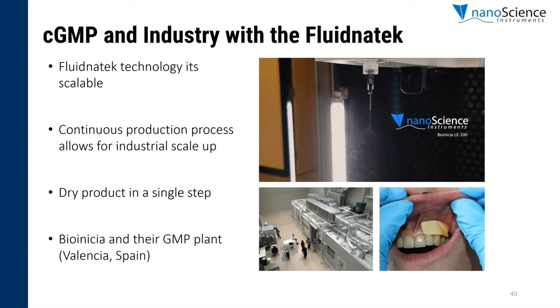Another important aspect about this technology is that it can produce a dry product in a single step, which is really important when using organic solvents because a lot of them can be toxic, for example, hexafluoroisopropanol or chloroform. Our units are GMP certifiable and scalable, allowing the technique to be even scaled to a production plant. We can easily increase the number of spinning heads along with the size of the machine, increasing the production rate into the industrial scale. As a matter of fact, Bioinicia has the first and only GMP certified plant to produce fibers for pharmaceutical applications and is currently working on developing a second GMP plant for particle development. Just as an example, with all these three images, we can go from only 1 emitter to a production plant and even have the finalized product using the Fluidnatek technology.